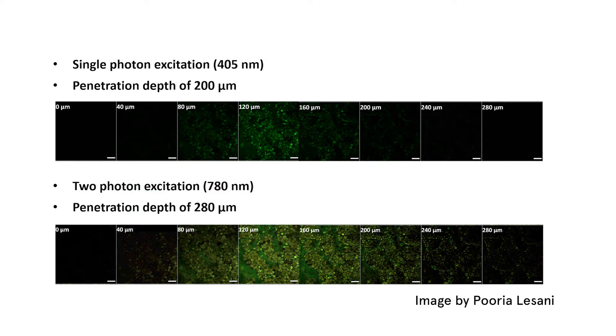Here are some examples to show the differences between single-photon and two-photon excitation. The carbon quantum dots have been incubated with pig skin tissue for imaging purposes. Fluorescence images excited by single photon show weak fluorescence signals with a maximum penetration depth of 200 micrometers; visible light excitation causes strong scattering which limits penetration depth in tissue. Using two-photon excitation, the penetration depth increased to 280 micrometers with higher resolution, demonstrating the ability of these probes for bioimaging and visualization of tissue structure.